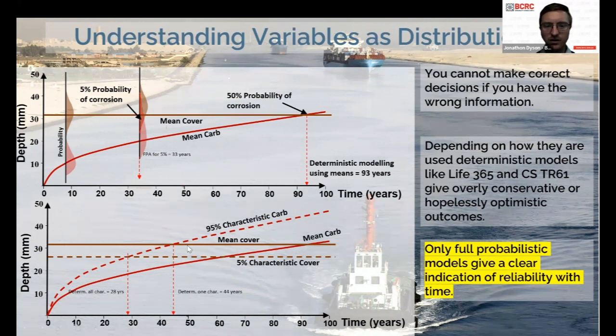So if you used a combination of characteristic, so for example, the characteristic carbonation and the mean cover, which you shouldn't really do, but sometimes people do that, then in this case, the deterministic modeling would give you 44 years. So yeah, it's really important that you understand what you are using, for all the variables that go into modeling, whether you're using a mean value, whether you're using a characteristic value.